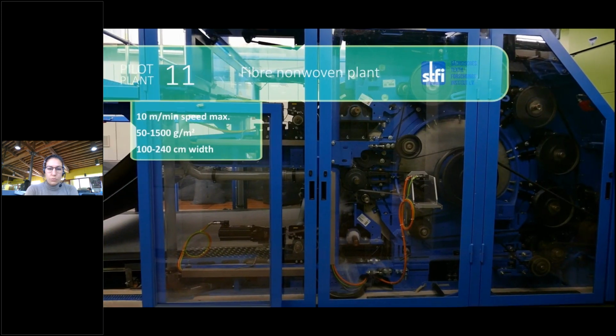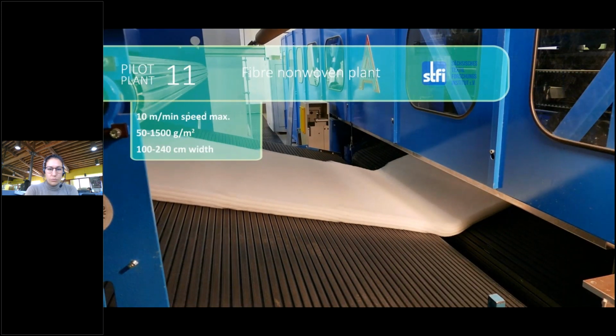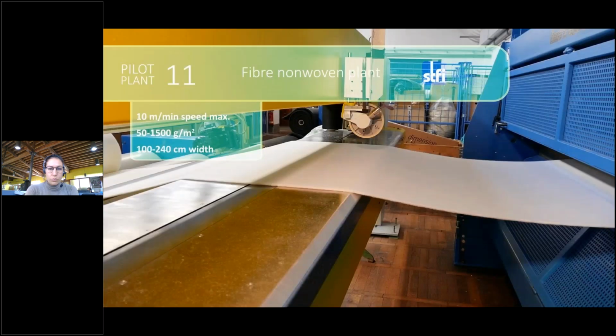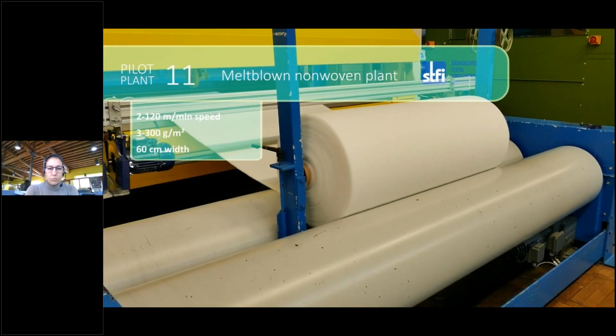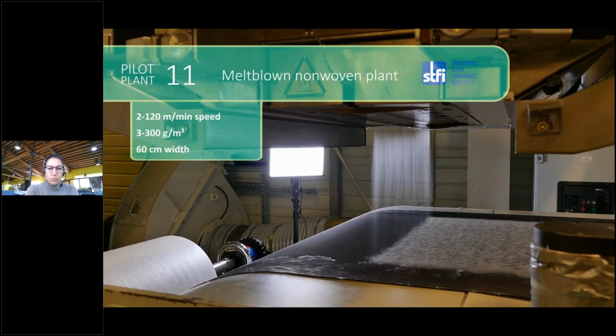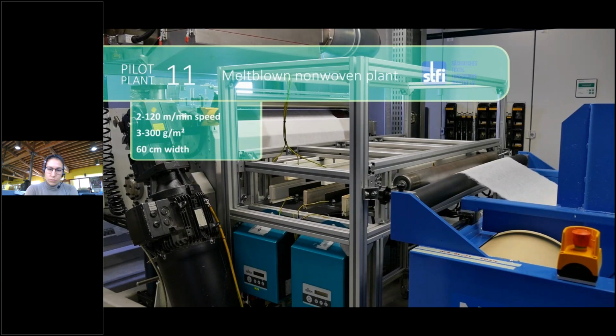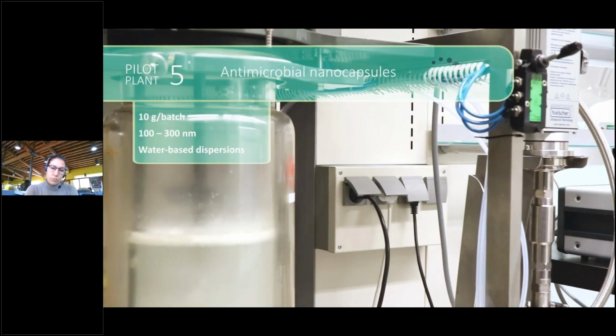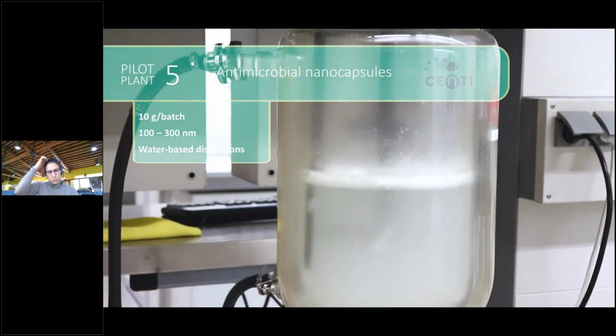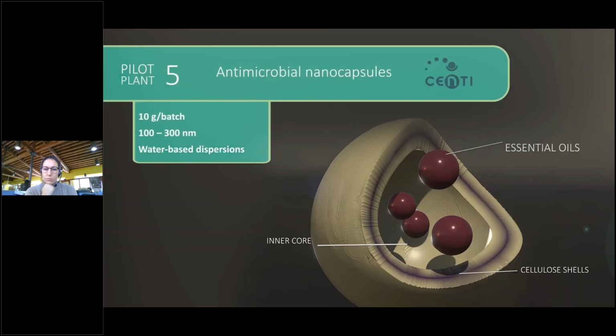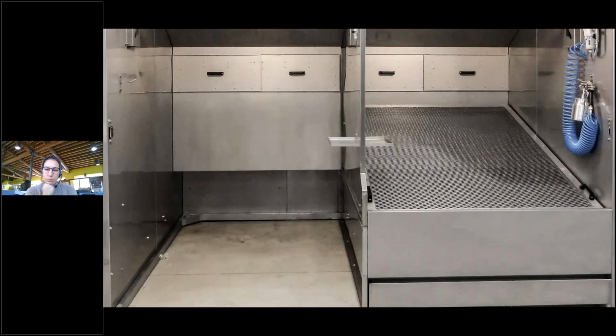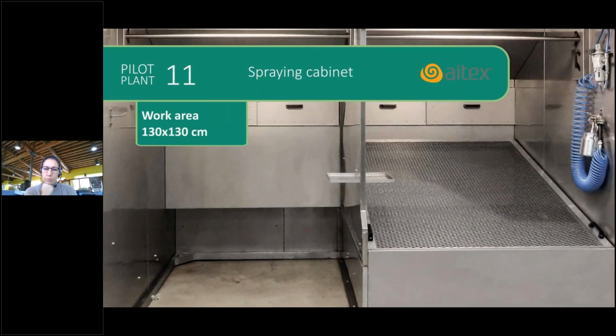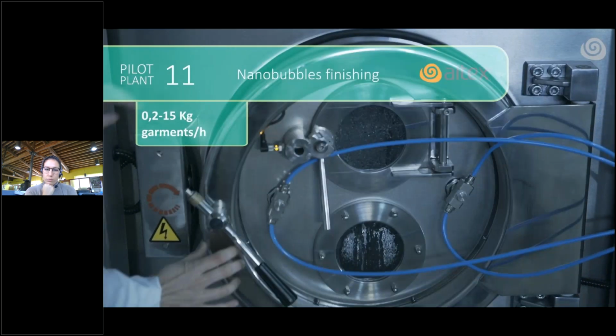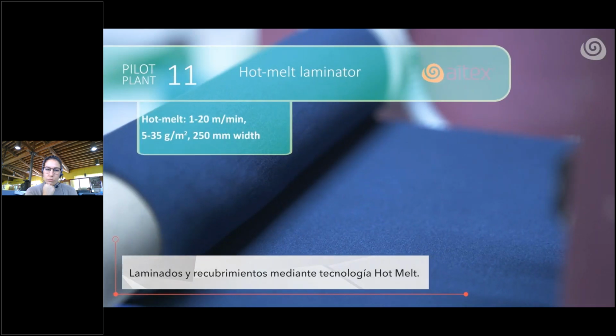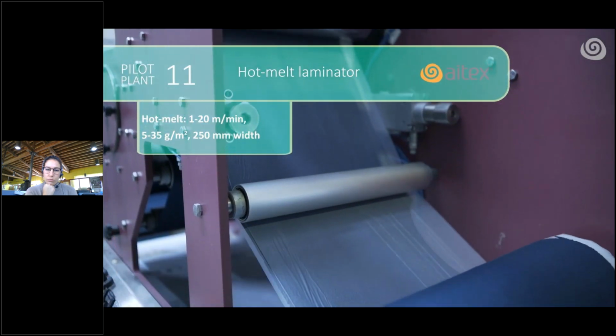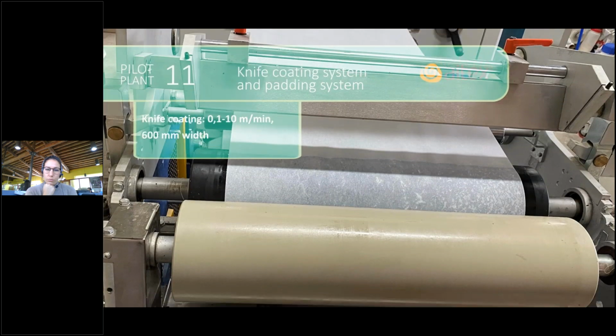Non-woven technology to generate non-wovens with specific properties by mixing staple biofibers with natural fibers, and melt-blown technology to obtain non-wovens of very fine up to ultra-fine filaments for filtration or medical applications. Through Pilot Plant 5, functionalized nanocapsules are obtained for coating on non-woven and textiles using Pilot Plant 11, which comprises spraying cabinet, nanobubble finishing, hot melt lamination, knife coating and padding system.